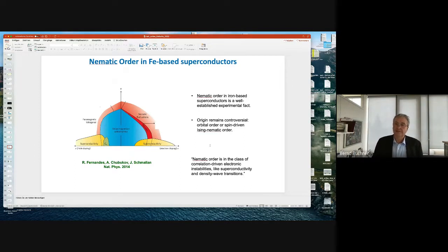And these are some statements which I took from this paper, also 6 years old meanwhile, that this nematic order, so this breaking of C4 symmetry in iron-based superconductors, is a well-established experimental fact. And still the origin remains controversial, and that's still the case until today, and I will address this a little bit. But there's also another statement, and I think this is also meanwhile justified, that this nematic order is, let's say, a new instability, which has been seen in clear fashion for the first time now in these iron-based superconductors, and now in the literature you will find a lot of examples where people discuss these nematic instabilities in other systems. So what about the origin?